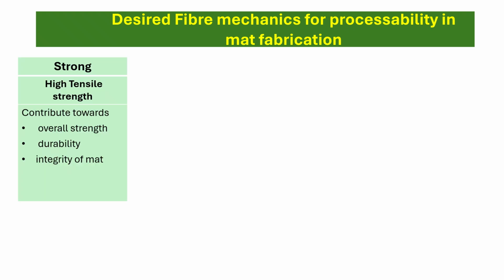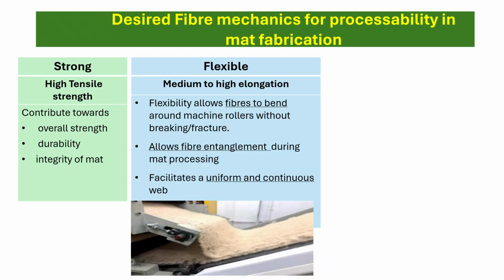So the fibers, first of all, they need to be strong, of course, because fibers with high tensile strength will imply that the overall strength of the final mat will also be strong, and this will contribute to the durability and the integrity of the mat. And the process that we used for the fabrication of the mat was the needle punching method. And so the fibers have to go through several stages of fiber opening, of fiber alignment, and they have to pass through cylinders. So the processing is quite mechanically aggressive, and so the fibers need to be flexible so that they can pass through all these stages without any fracture or breaking.